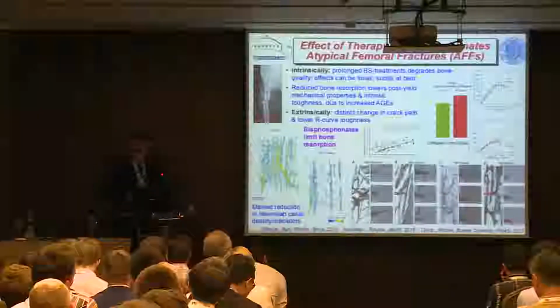We also see excessive cross-linking. This is the cross-linking in bisphosphonate-treated bone. This is regular bone. So there's also a loss of ductility. But again, you can see there's these two contributions to the problems of toughness. And this is not unusual.